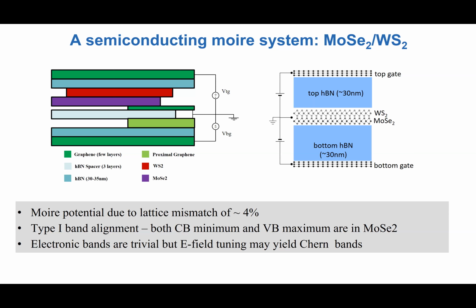What is special about this Moire system is that it has a type 1 band alignment. There are only two that I know of which have this. That is basically the minimum of the conduction band and the maximum of the valence band are in the same material. There's a potential, but let's say the conduction and valence bands haven't moved spatially over the minimum band.